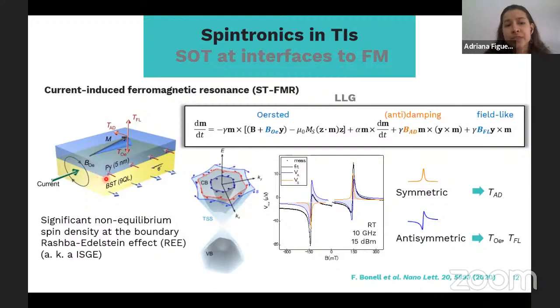Okay, so that spin accumulation is able to exert a torque onto this ferromagnet that is at the interface, and with that you modify the magnetization dynamics of the ferromagnet, and you could also switch the magnetization in the material, and that's what we're interested in. We're interested in having that level of control and manipulation of the magnetization on that ferromagnetic layer as a consequence of the electrical properties, of the electronic properties of that TI.